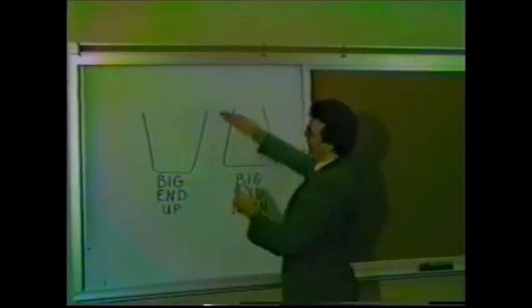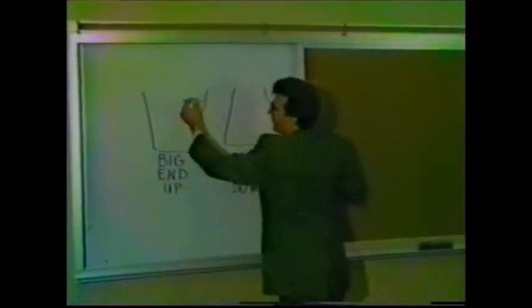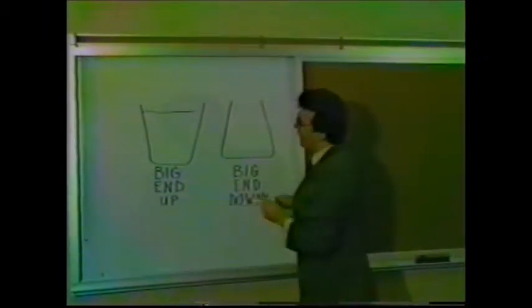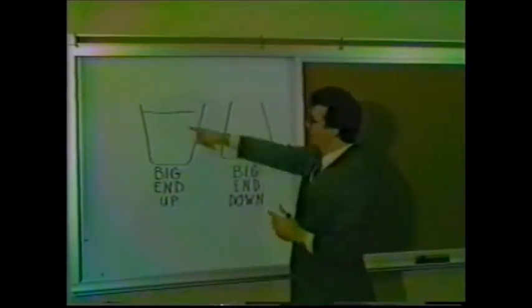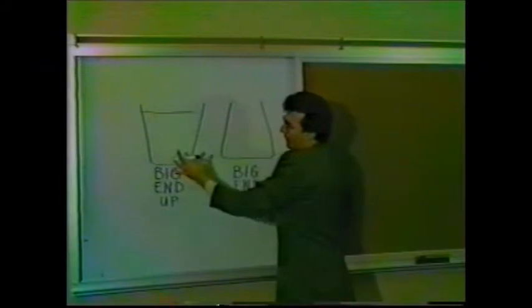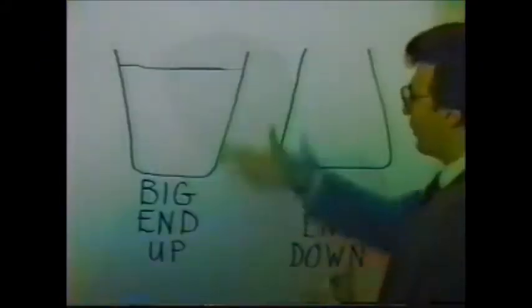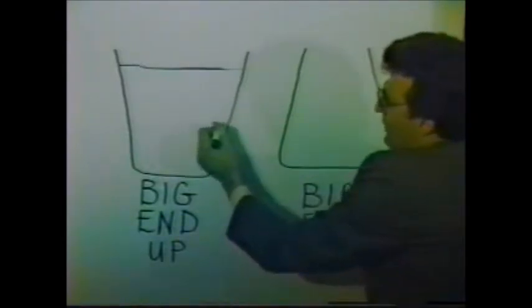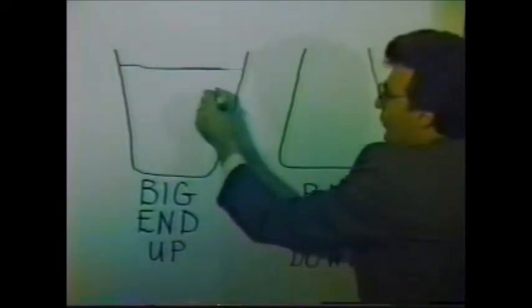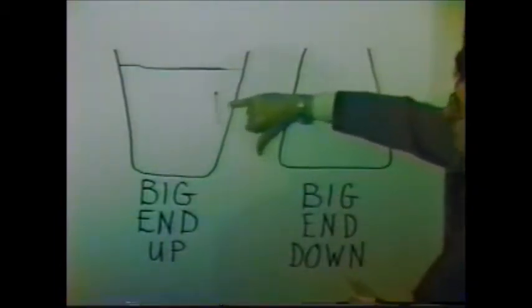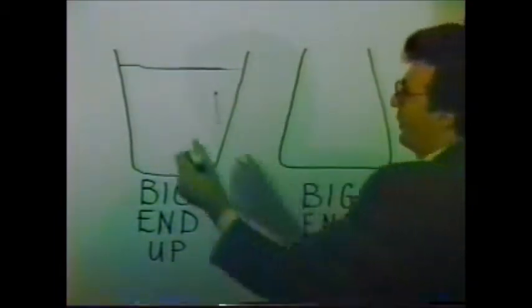A mold may have its big end up or its narrow end up. These are also known respectively as big end up and big end down molds. Now, each shape has its own advantages and a cost associated with it. With the big end up molds, the steel is poured in from the top, and the main advantage is that as the steel is poured in, the steel will start to effervesce and give bubbles. As these bubbles start to form and float up, they actually float away from the surface of the ingot mold, as you can see.